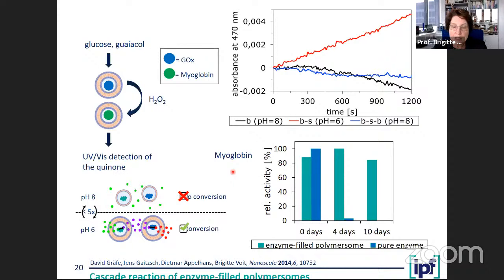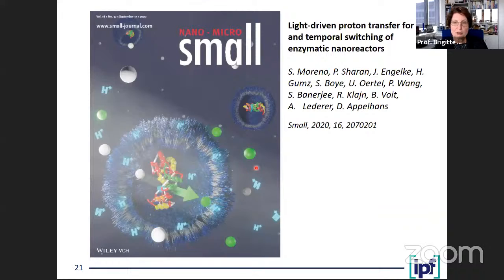We are presently also studying much more complex enzymes, which are not for model reactions, but which are, for example, also used for the production of specific drugs. So I hope I could convince you that's very nice. So you can make such a polymersome. The polymersomes we prepare are in the range of 100 to 150 nanometers in diameter. We can really use them for a lot of interesting reactions. That's a very recent publication where we also used a light-driven proton transfer. So by light, protons were created, and that finally allowed the transport into such polymersomes and also the activity of enzymes which had been encapsulated.